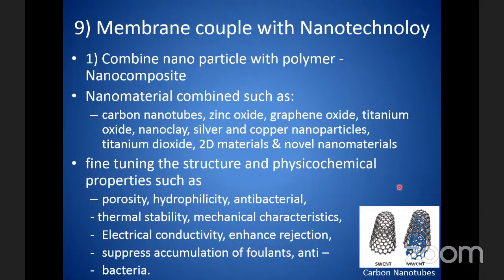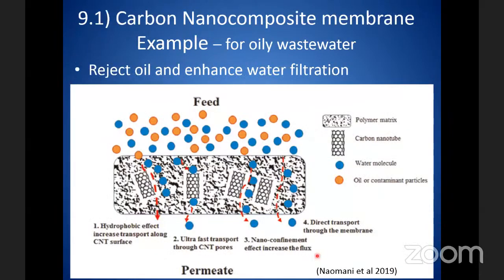These are on the lab scale and pilot scale. Enhanced rejection, suppress accumulation of foulants. So you use UV or something else, it will oxidize those foulants, and it will also be antibacterial. So that's how it works. Instead of putting in the coagulant or polymer that we shared just now, now they embed or coat all this nanomaterial together with the membrane. So this type is using nanocomposite. The nanocomposite means they combine the nanoparticle, the material, into the polymer, blend into it, and then they make it into membrane.